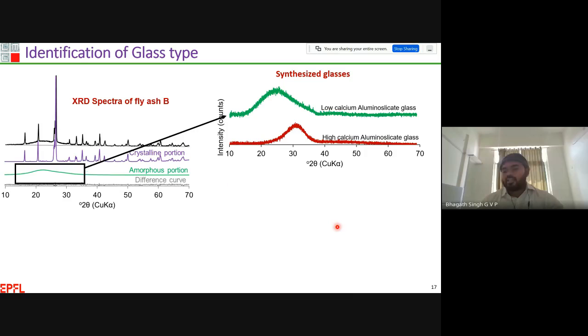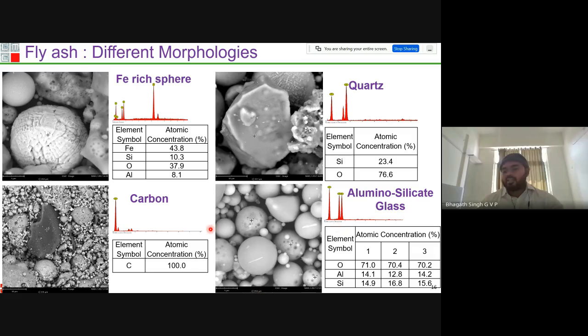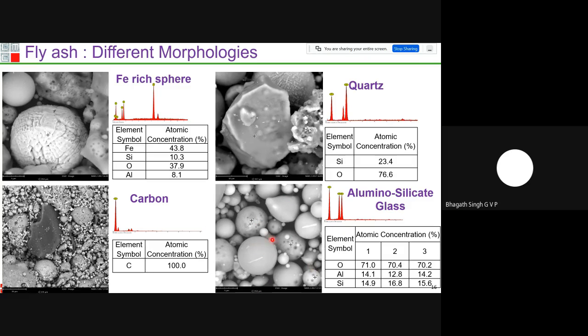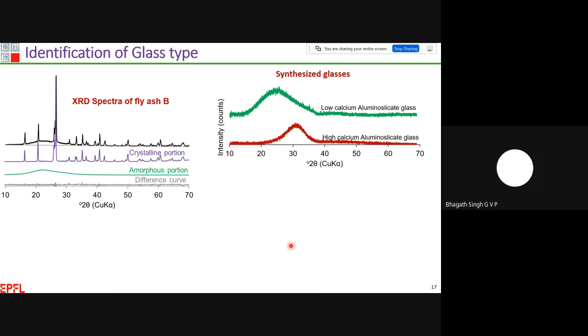So it was evident from the previous EDX analysis that these particles are rich in aluminum silicate glass, but we had not defined whether they are calcium rich or low calcium. But as per our synthesized glasses, it was evident that most of these fly ashes contain the low calcium aluminum silicate glass.